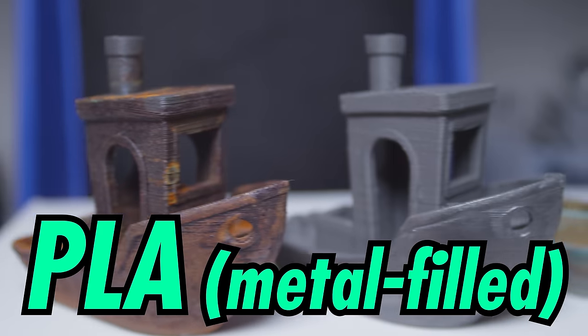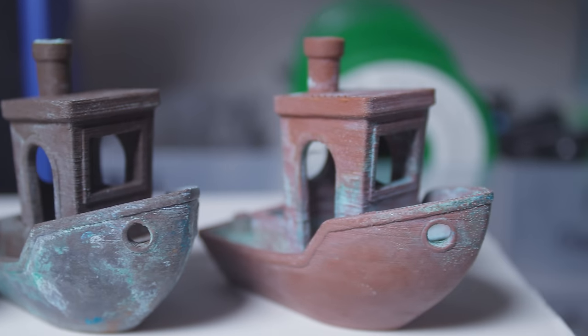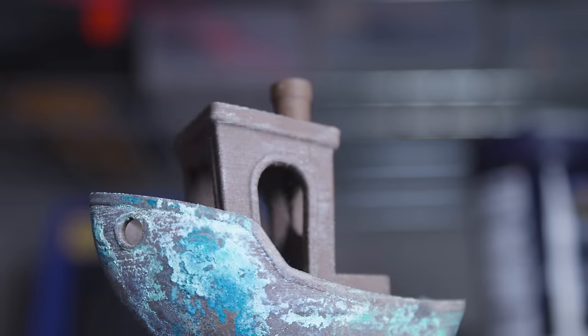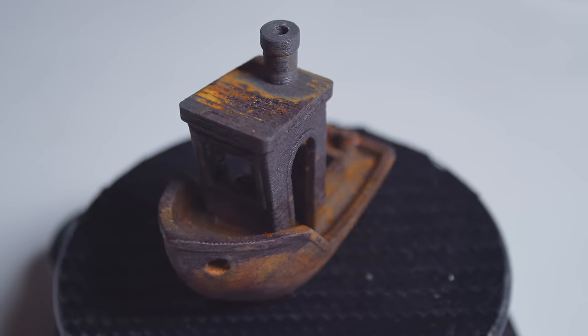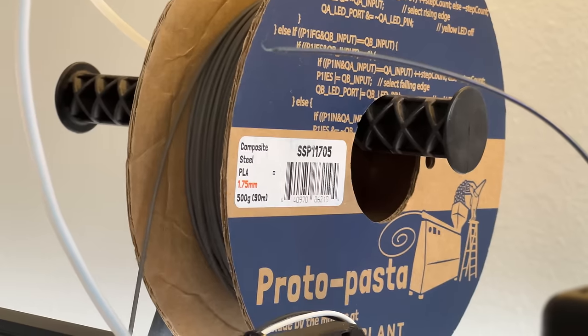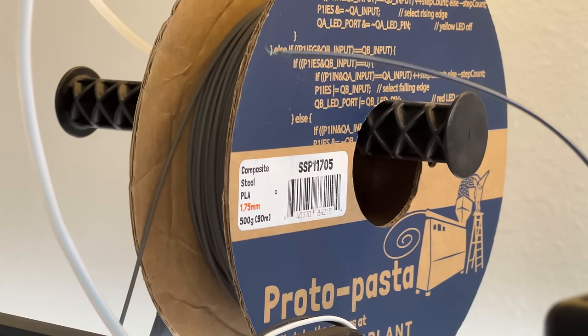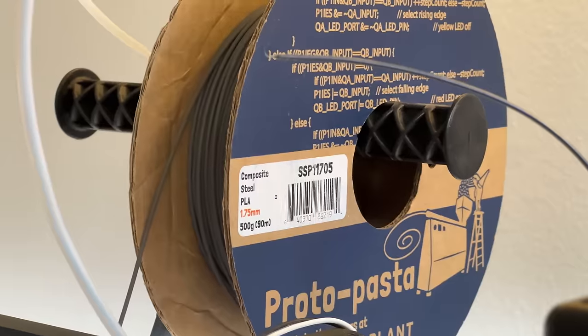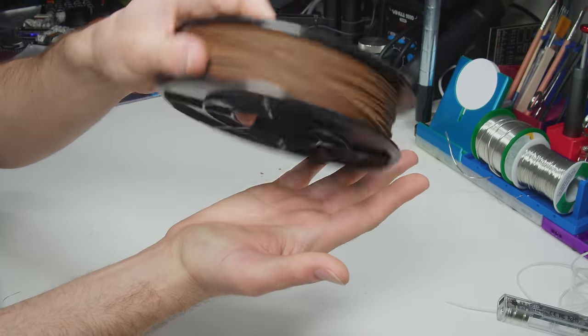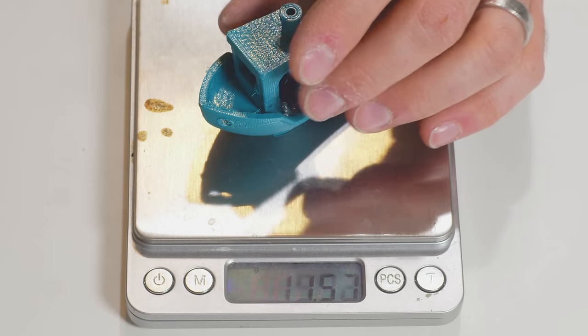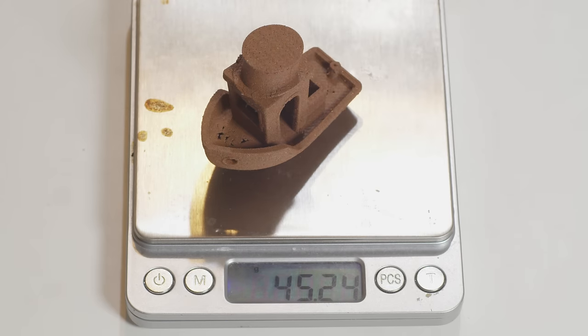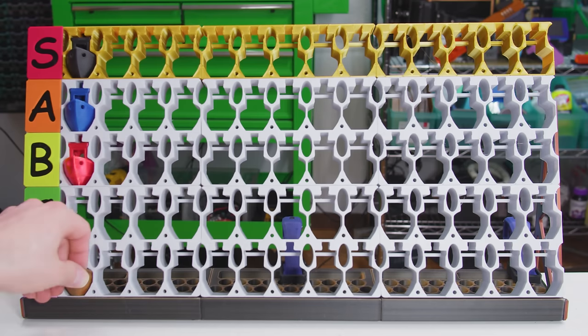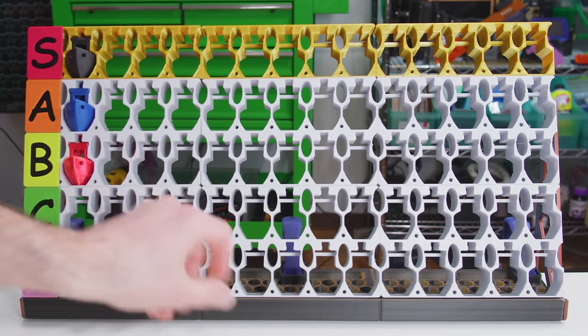So what about a composite with metal? Infusing your prints with metal shavings makes them satisfyingly hefty and adds a little bit of their properties. Copper will develop a green patina, stainless steel can be polished, iron is magnetic, you get the idea. The metal doesn't make the filament any stronger, the stuff is actually significantly weaker than vanilla. Unfortunately, metal-filled filaments are extremely brittle on and off the spool, and they are crazy expensive. You pay far more per gram, and because the filament is so high density, you get fewer prints per gram. Anything these can do, you could do better with a regular filament and a coat of paint, some inserts, or even some electroplating. I'm gonna put the entire category of metal composites in F.